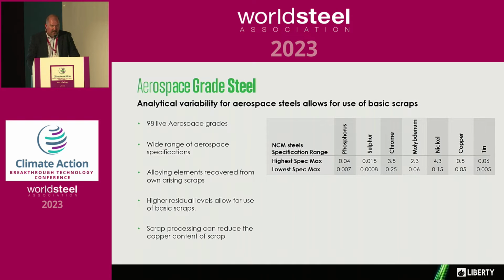Highlighted on this slide is the range of analysis across 98 live aerospace grades currently on offer from Liberty Speciality Steels. Alongside challenging levels of phosphorus and sulphur at the lowest end of the range, you will also recognise the 0.5% variability in copper plus tin across the whole range of grades. Low residual scraps required to dilute the residuals from other scraps are required in volume at the extreme low end of this range. The most extreme example requires up to 50% of the charge weight to be low residual scrap. With scrap cleaning, it is possible to reduce the overall requirement for low residual scraps for cast final analysis aims in the middle of this product range, and it's even possible to eliminate its requirement in full for analysis aims at the upper end of this range.